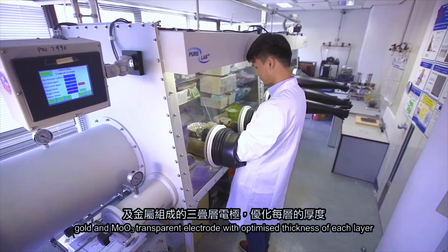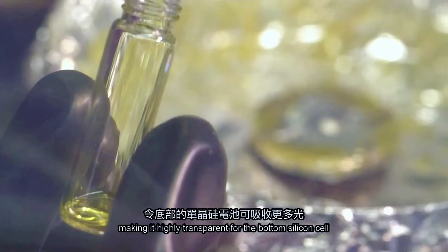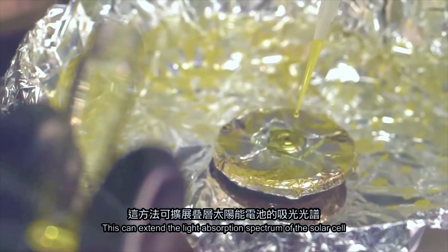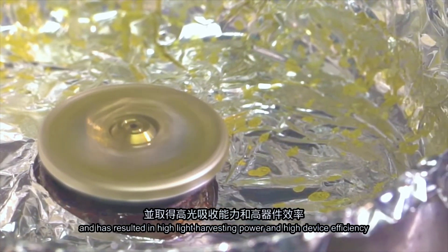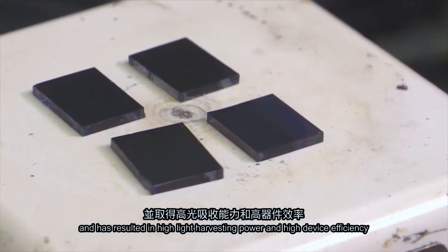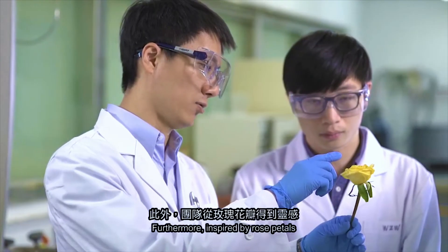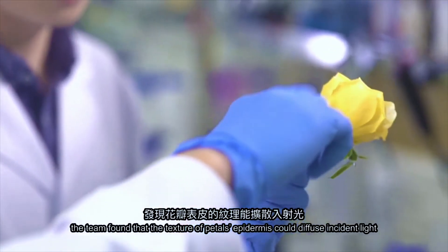The first design consists of perovskite layers deposited from a liquid solution onto a flat silicon surface, which achieved a 30.93% efficiency for a 1-square-centimeter test cell. The second used a hybrid vapor and liquid solution approach to deposit perovskite onto a textured silicon surface, achieving a 31.25% efficiency for a 1-square-centimeter solar cell.